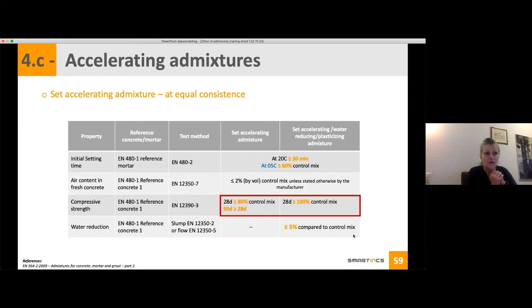If you use a set accelerating admixture that also has a plasticizing effect, at 28 days you should get at least the same strength as your control mix. And in that case, it means it is also an admixture that will show at least 5% of water reduction.